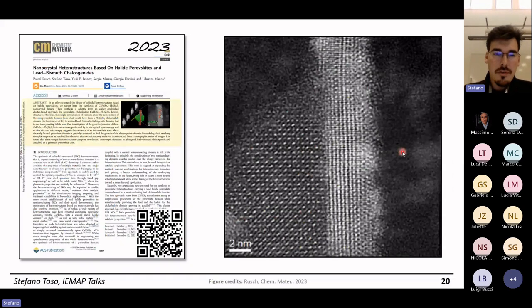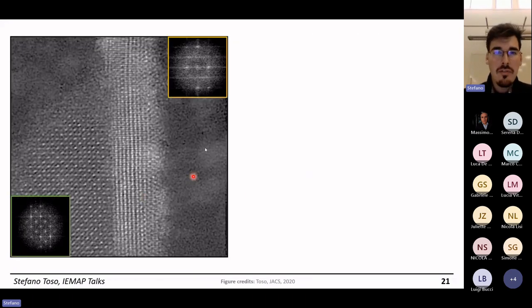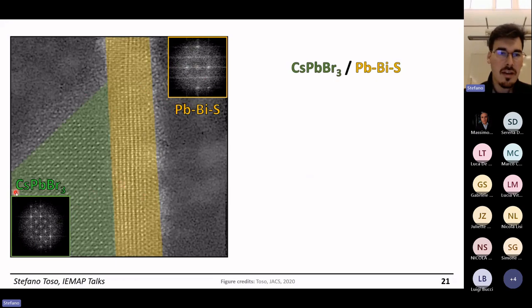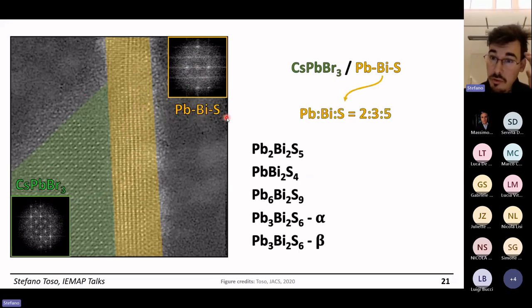Another interesting case that was also financed under the IEMAP framework is this situation where we have a perovskite domain and a rod that is growing on top, and we were trying to figure out what this material is. We were struggling because, from the Fourier transform of the lattice, you can identify that this is cesium lead bromide, and you have an idea that this rod is probably a mixed lead bismuth sulfide. But there are a lot of mixed bismuth sulfides, at least 5 phases, probably more. They can form alloys between each other, and they all look similar crystal structure-wise. So it's difficult to resolve which of the 6 is the real case.